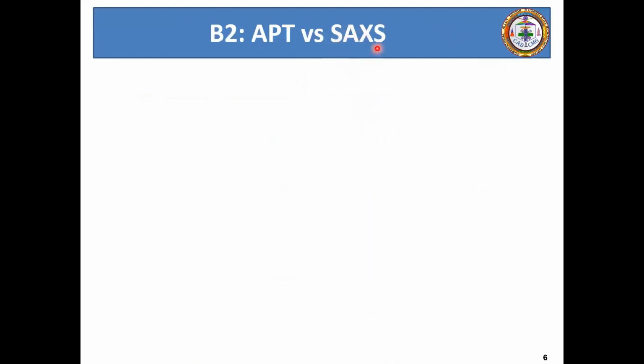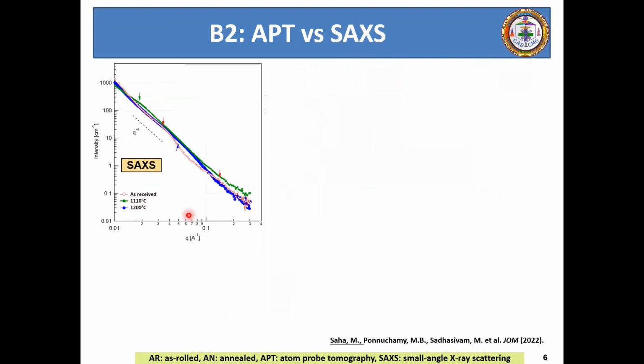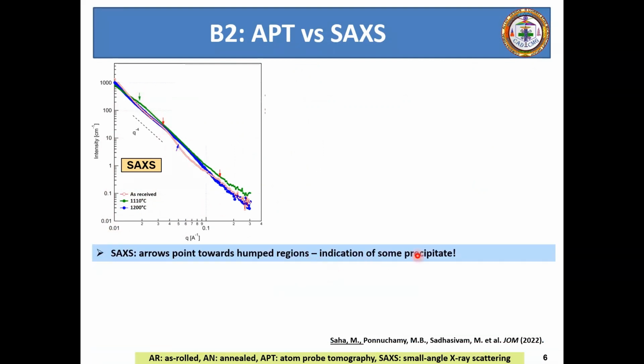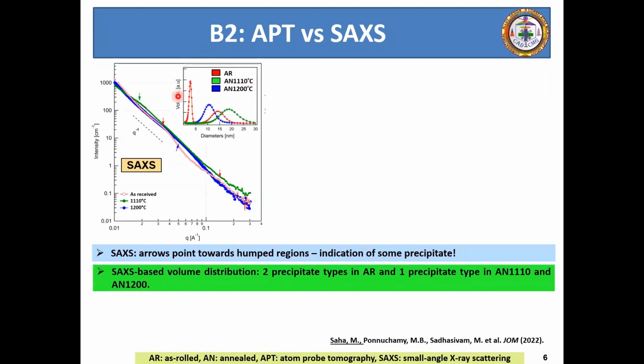performed the SAXS analysis, or the small angle X-ray scattering experiment, in three different conditions, that is, the as-rolled, the 1110 degrees and the 1200 degrees annealed conditions. And these are the SAXS-based intensity profiles shown as a function of the scattering vector, where the arrows pointing towards the humped regions basically indicate the presence of some precipitate. And when we further perform the volume distribution analysis in these three different conditions as a function of the particle diameter, what we can clearly see, based on these peaks, is that we have two different types of precipitates in the as-rolled condition, whereas only one type of precipitate is present in each of the 1110 and 1200 degrees annealed conditions.